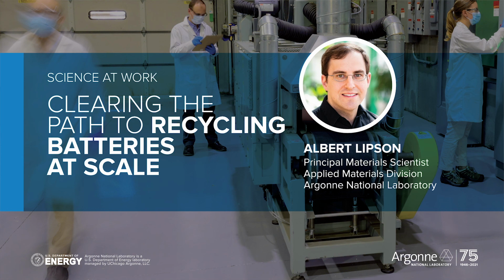So I can take that one if you want. So we actually do have some initial modeling of these processes in our model that is known as EverBatt, that was developed here at Argonne. So in that model, we actually see that direct recycling dramatically reduces the impact of the recycling process from the perspective of energy, as well as carbon dioxide emissions from the process. This is because we don't have to go through a lot of the extra steps that they do to go back to the raw materials and then remanufacture the cathode material. And so we eliminate a lot of that.